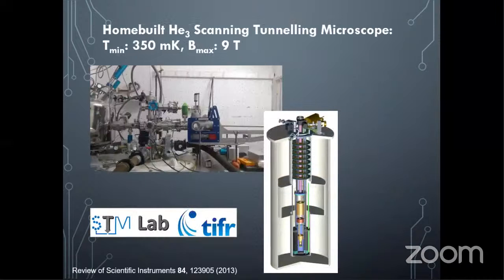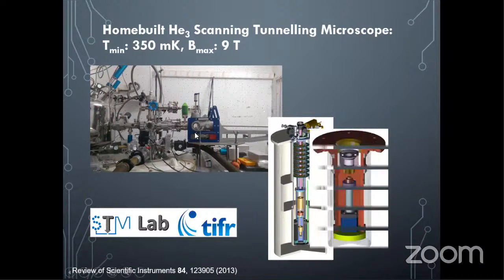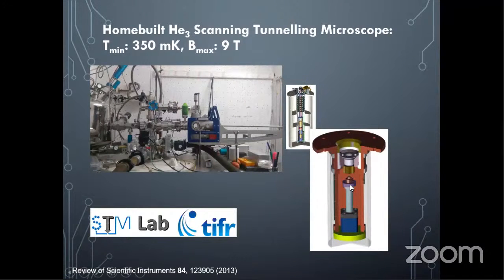Now, this is a photograph of the scanning tunneling microscope at TIFR. This is used down to 350 millikelvin, and there's a superconducting magnet inside where one can apply a 9 Tesla magnetic field. So this is the system which Professor Pratap Raychaudhuri works on, and Shurojit is currently working on this system. Here there is a platinum-iridium tip which is used to scan the surface of the sample.